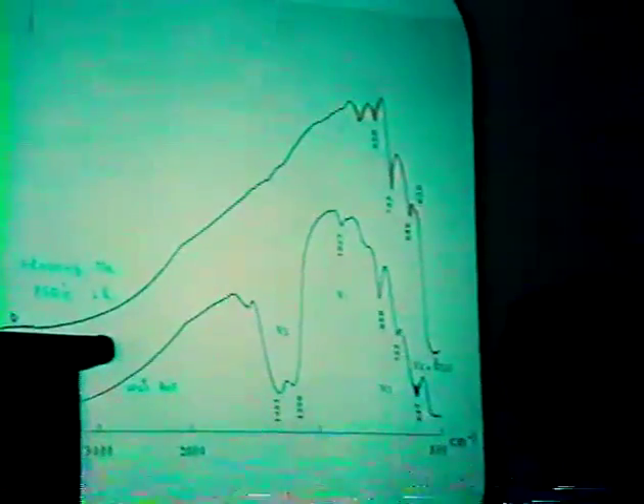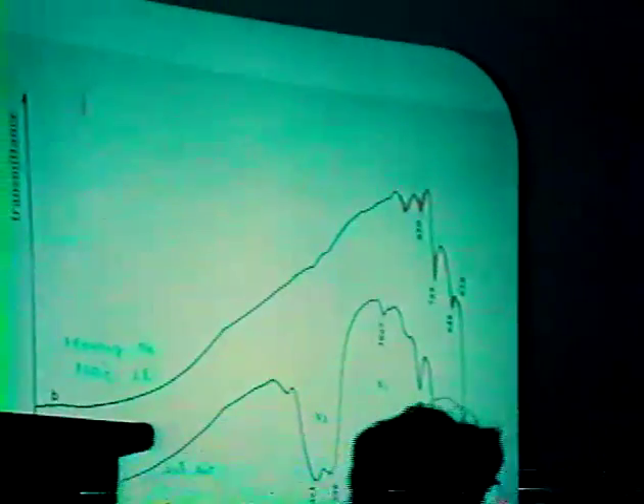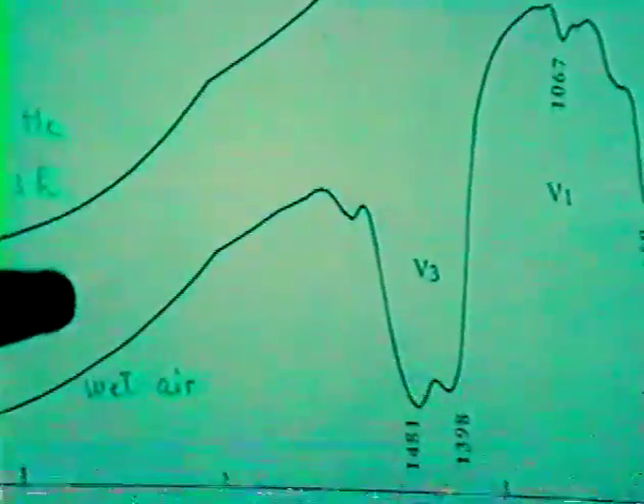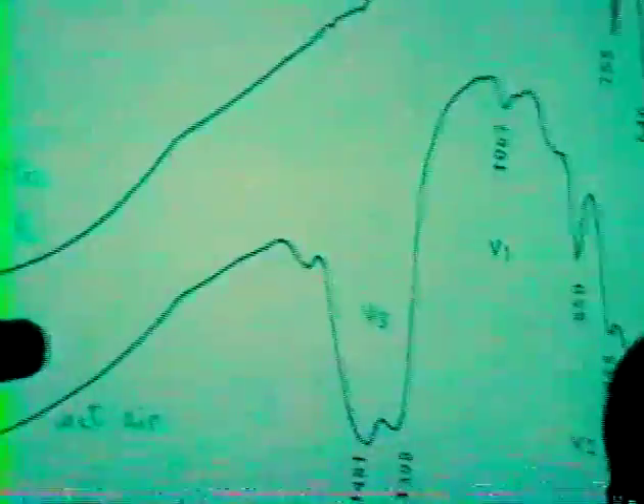So here is represented the spectrum of the catalyst after exposure to wet air. You can see, besides the characteristic vibration of the carbonate ion, the stretching and bending OH vibration of hydroxyl, which characterize the hydroxide. This hydroxycarbonate species can be destroyed by flowing helium at very high temperature, since the most intense band of the carbonate species disappears.